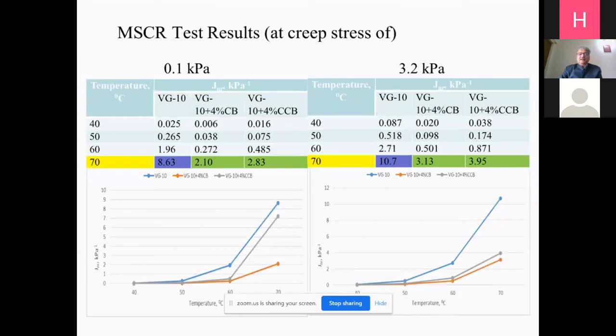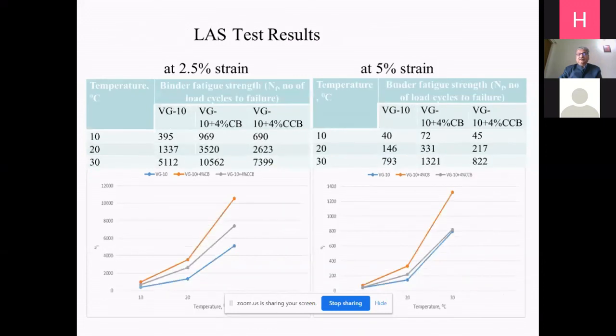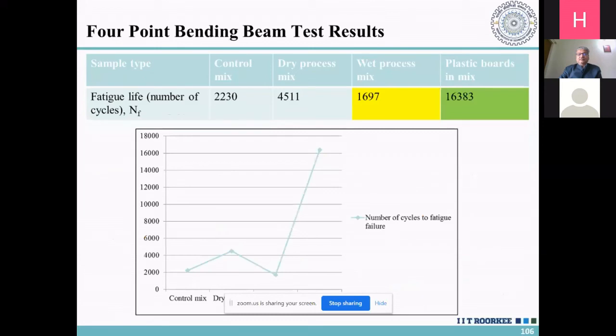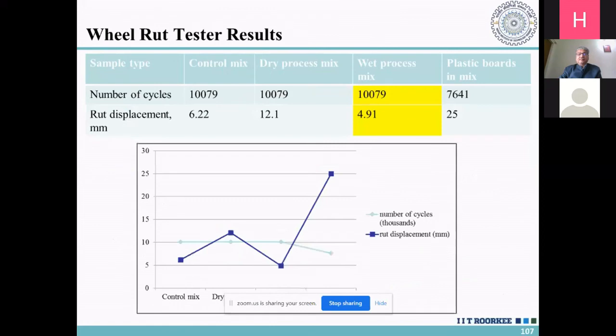Then MSCR test, it is also a test regarding the rutting. It also tells you the improvement when we are using 4% cement bag or cement carry bag. This is the LAS test, that is a linear amplitude sweep test, which is telling about the fatigue. This is 4-point bending beam test result. This is also about the fatigue.